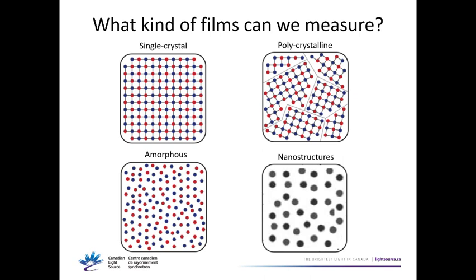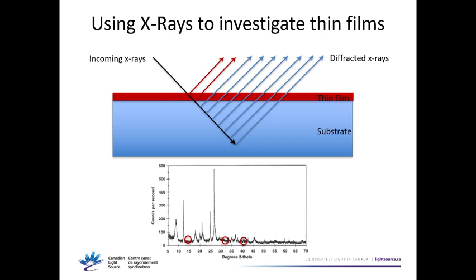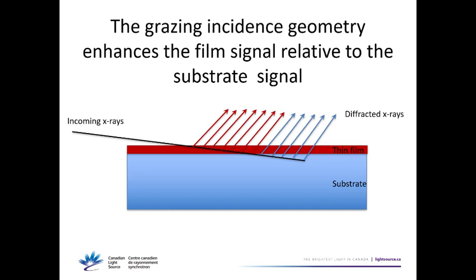We can apply these techniques to a large variety of films — whether they are single crystals, amorphous, or polycrystalline thin-films, or nanostructures on a substrate. Going back to our initial slide, steep incidence was not a good way. Coming at a grazing incidence is better — the X-rays attenuate more significantly in the film and less in the substrate, so the signal recorded in the detector increasingly comes from the film the more grazing you go.